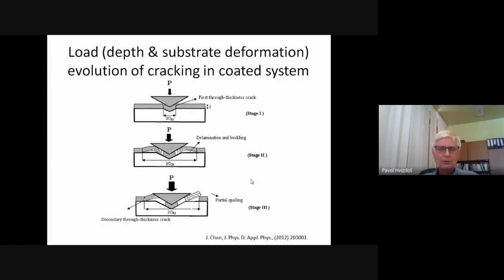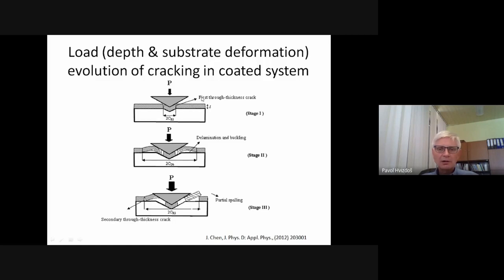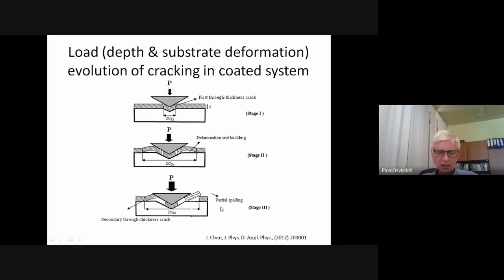These two families will be the main topic of the current talk. The appearance also strongly depends on the loads applied and the deformation of the substrate. Through-thickness cohesive cracks first appear at relatively small loads. At much larger loads, lateral or adhesive delamination cracks appear nearby the indent, and finally, if these two crack types connect, spallation or large-scale delamination can occur.